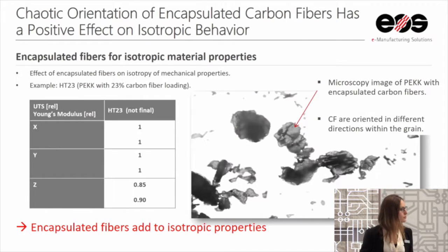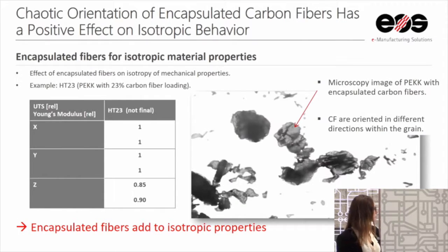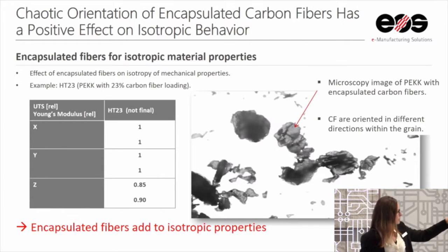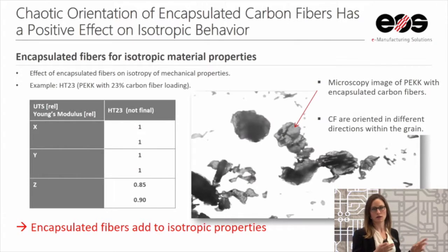So if we look into outcomes of that exercise, you can see on the picture, it's a microscopic picture, and I'm going to have some more on that. On the right-hand side, you see there's the particles of the PEKK, and you see some carbon fibers in there, and they have a kind of chaotic orientation, and that really helps for the isotropic behavior of the material. On the left, I have this very basic but still little table that shows the relative values of X, Y, and Z for the tensile strength and the modulus. And you see Z is still not the same as X and Y, but it's pretty close.